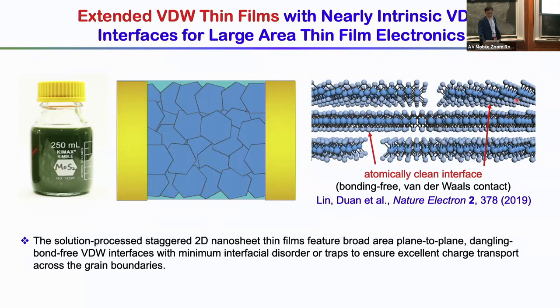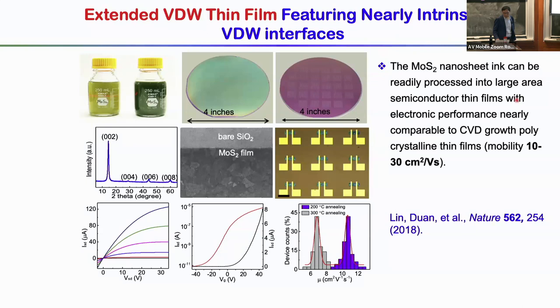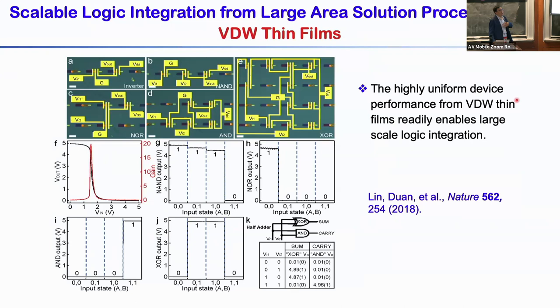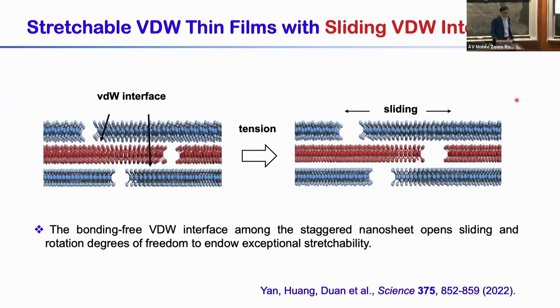We demonstrated this concept a few years ago by making high-quality 2D nanosheet inks that can be easily deposited over large areas as thin films, with very decent electronic properties — carrier mobility around 10 to 30 cm²/V·s. Because we can process over large areas, we can think about scaled device design. But more interesting is that this thin film, unlike conventional inorganic thin films, has a stack of nanosheets with van der Waals bonds — so if you try to push them, the nanosheets can actually slide on top of each other without breaking the electric contact. This gives us the possibility to create a stretchable thin film.